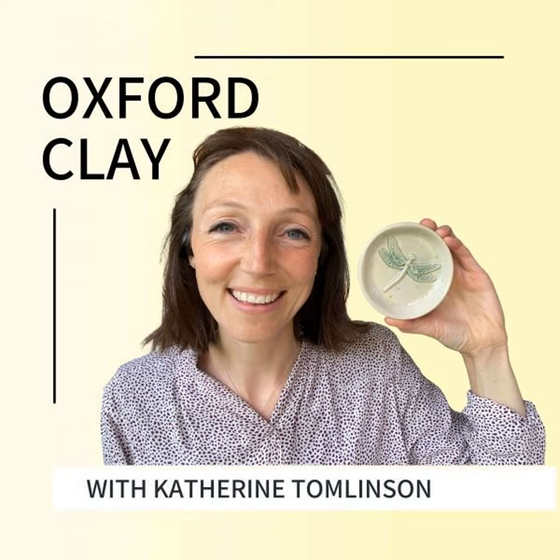So I hope that's clarified the difference between earthenware and stoneware. It's basically just the range of temperature at which that clay reaches maturity, and beyond that it will start to melt. There's another factor to this, and that is that glaze firings are divided into earthenware and stoneware glaze firings. You might have heard people talking about low fire or high fire glazes. That's a term used in pottery. And you might have even heard people refer to cone 06. That low fire, cone 06, earthenware, that's all the same temperature range. And then high fire would be cone 8, 9, 10. Those are the stoneware firing range of temperature.